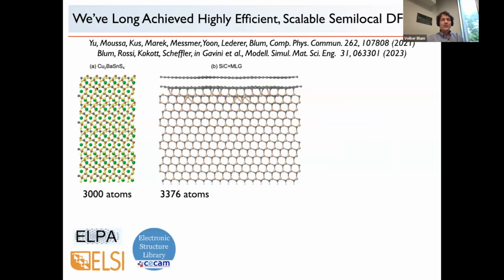It focused on a heavy element system, copper barium tin sulfide. This is a semiconductor that may have its own uses in photovoltaics. But the key point is that we had a 3,000 atom model here to show that we can actually scale for heavy atoms and heavy elements, not just for some toy system. And this is a system that we worked on for a long time in my group as well, monolayer graphene on a silicon carbide slab.